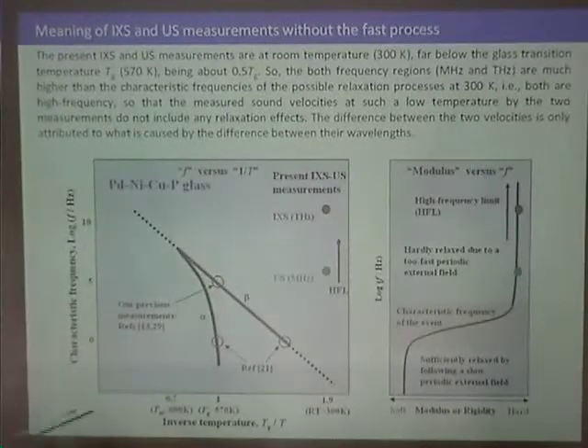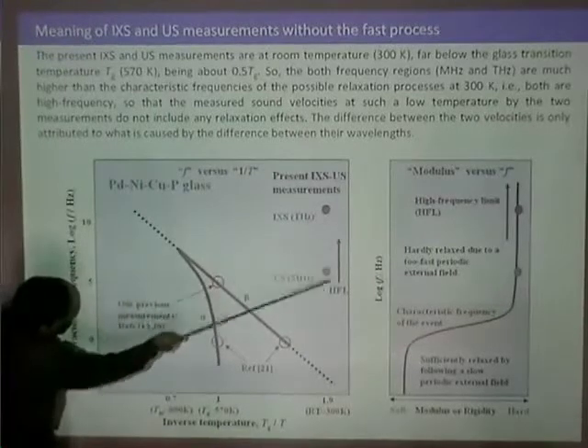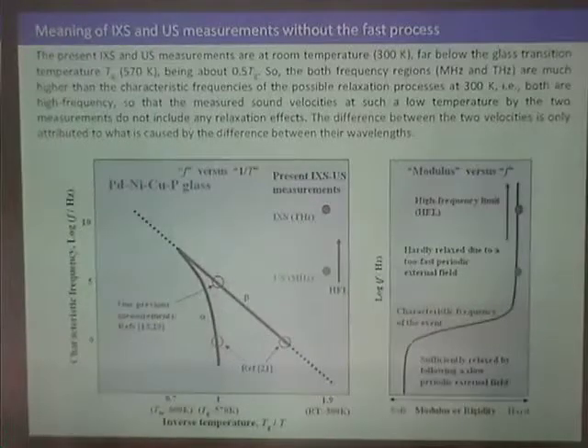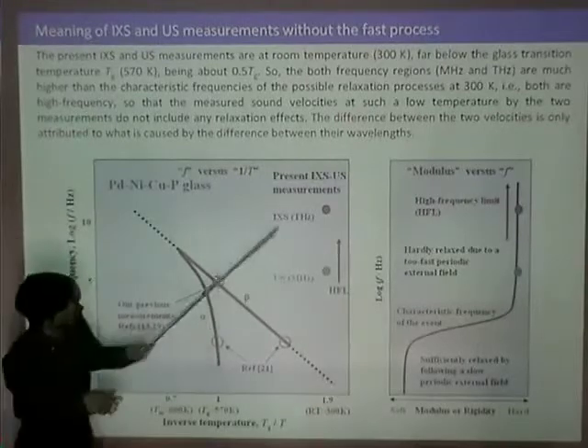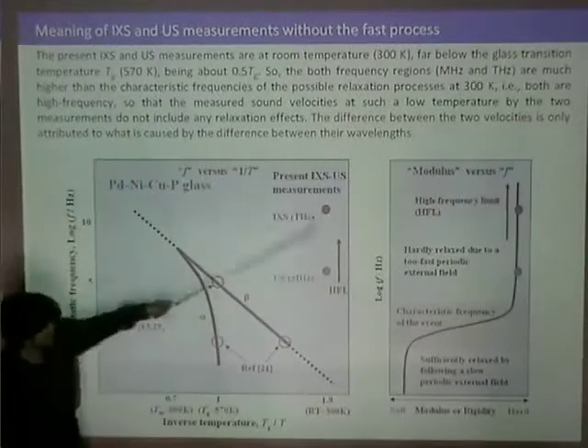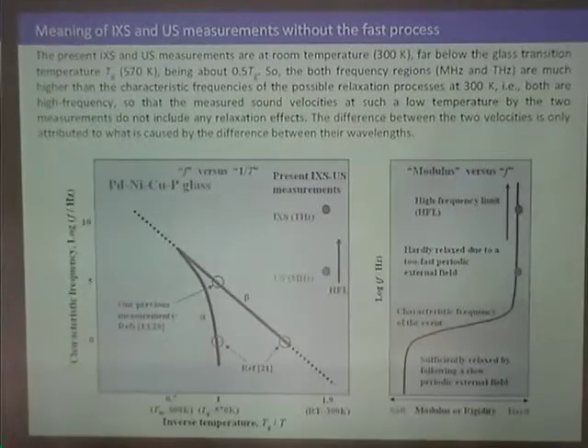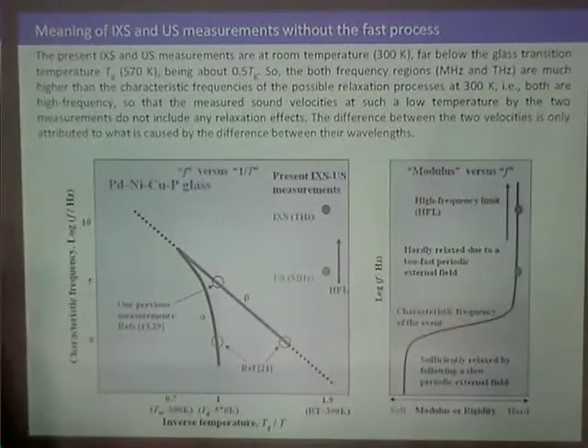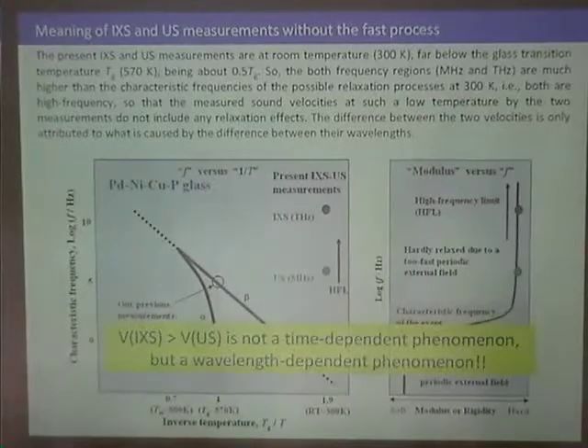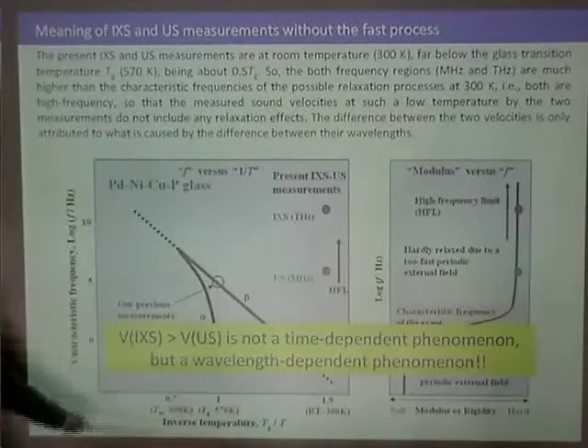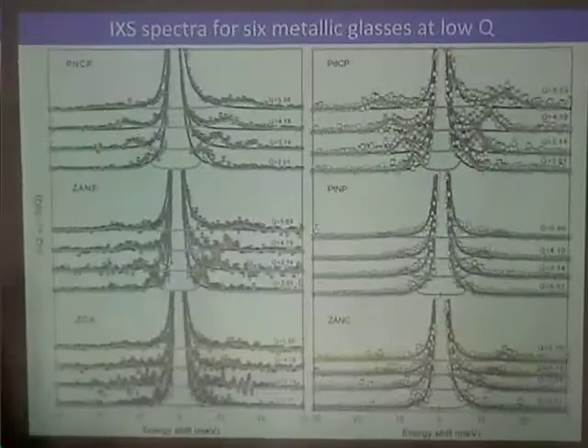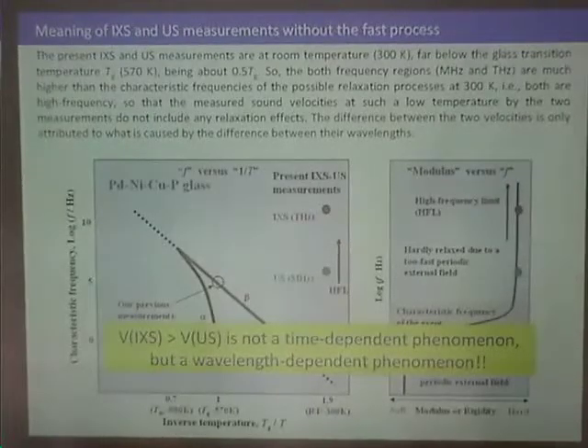Therefore, the difference in the elastic constants between the two methods does not include time dependence. Probably this is due to wavelength dependent phenomena. So then, would you expect that if you did experiments at much longer wavelengths, you might see damping, for example from the beta relaxation?